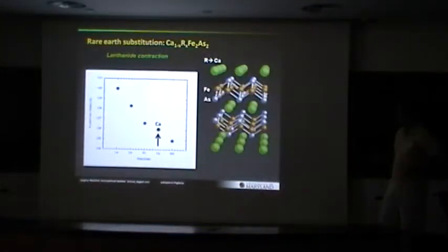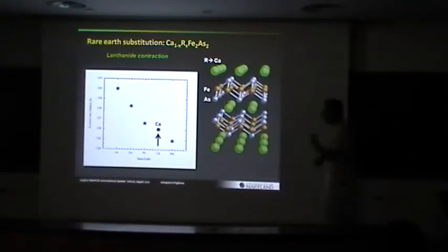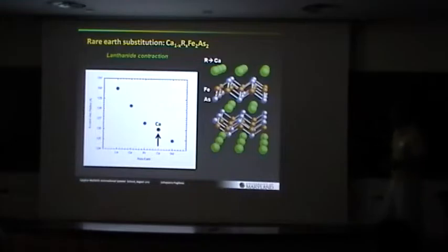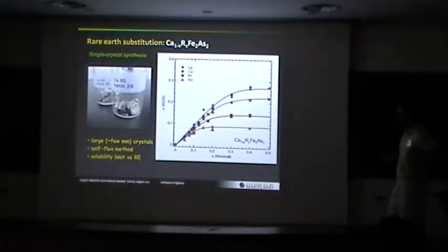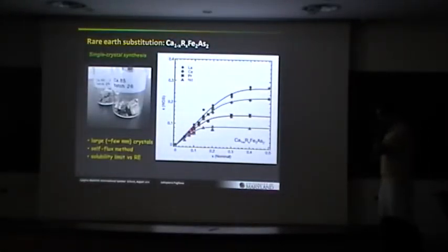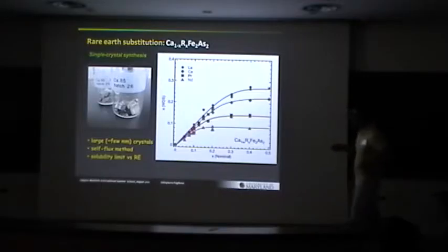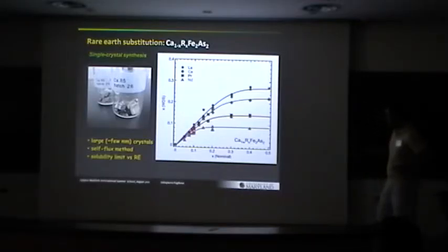Okay, so it turns out that calcium, if you just take the ionic radius, is somewhere between praseodymium and neodymium. This is just the elemental ionic radius for an eight-coordinate condition. In reality, it turns out to be more like somewhere over here with respect to these light rare earths. But it's a very close match, so this is why we can actually grow these crystals. Okay, so here are results on all single crystals.